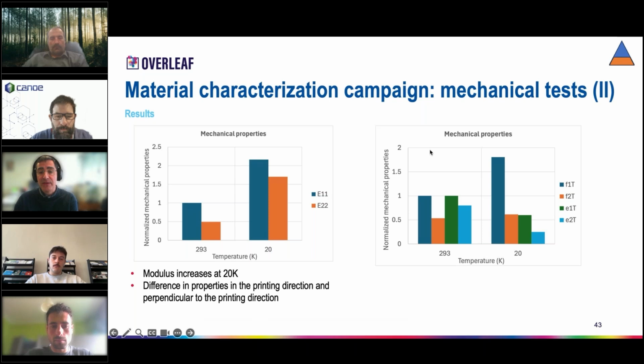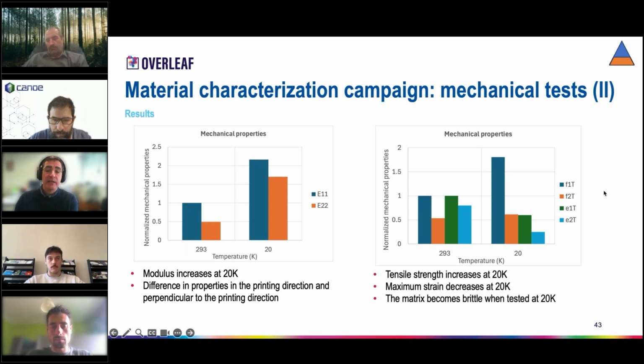On the other hand, we have the strength and ultimate strains. F1 or F are the stresses, E are the strains, 1 is the printing direction, 2 is perpendicular to the printing direction. Again, we have the two temperatures and the normalized mechanical properties with respect to the stresses at room temperature in the longitudinal direction, and strains here in green at room temperature with respect to the longitudinal direction. Here we can see that the tensile strength increases as we go down. The maximum strain decreases, so the matrix becomes more brittle when tested at 20 K. So we have to take this into account in our analysis.